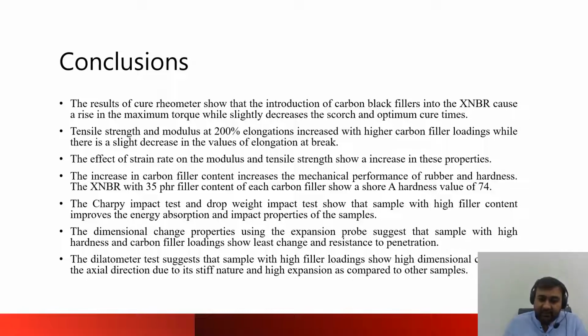The effect of strain rate on the modulus and tensile strength shows a slight increase in these properties. The increase in the carbon filler content increases the mechanical performance of the rubber and hardness, and the XNBR with 35 phr filler content shows the maximum hardness value of 74. The Charpy impact test and drop weight impact test show that the samples with higher filler content show the maximum energy absorption and impact property.